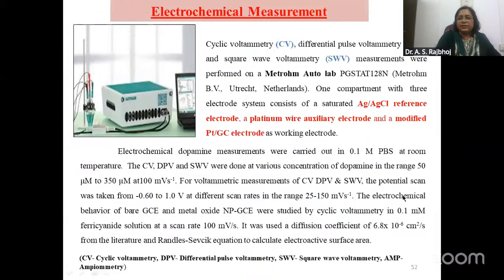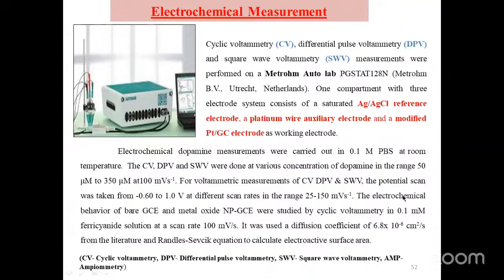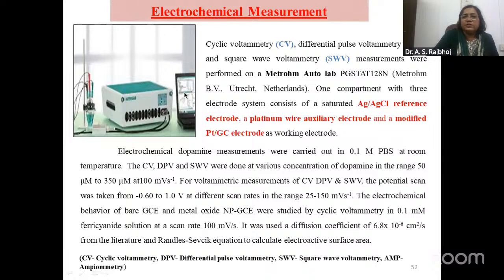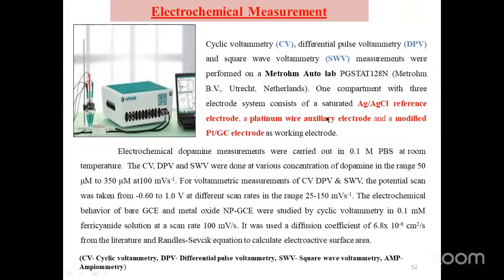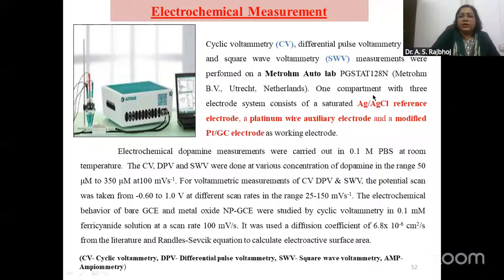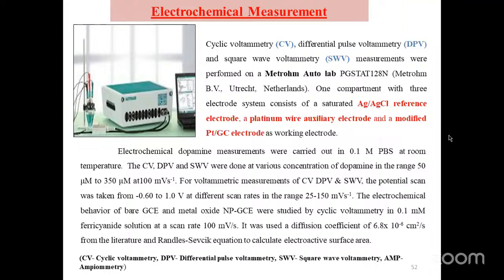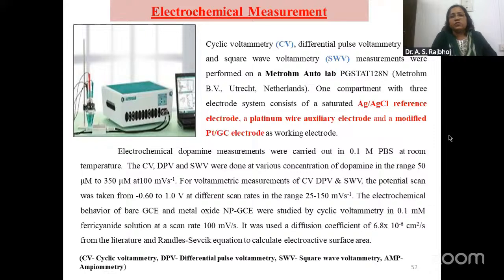So what we have done is that we have used the Metrohm PGSTAT, on which we can study cyclic voltammetry, differential pulse voltammetry, that is DPV, and square wave voltammetry measurements. This instrument consists of a three electrode system: Ag/AgCl as the reference electrode, a platinum electrode, and a modified glassy carbon electrode as the working electrode. Here we are carrying out electrochemical studies of dopamine in 0.1 molar PBS at room temperature. The CV, DPV and SWV were carried out at various concentrations of dopamine, in the range of 50 micromolar to 350 micromolar, at 100 millivolts per second.